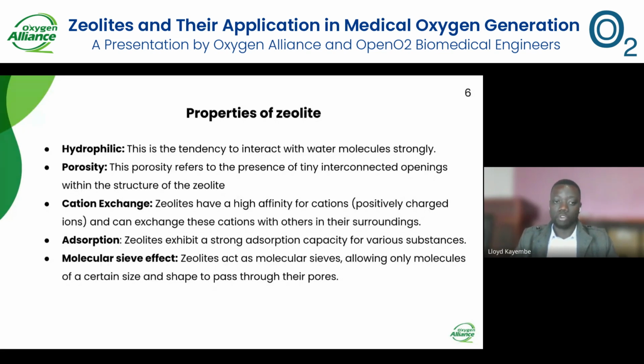The other property is porosity, and this just refers to the presence of the channels and the pores within the structure of the zeolite that allow molecules of smaller size to pass through. As I've said, the sizes of the pores are influenced by the cations that are present in the structure. In the synthetic zeolite that I was talking about earlier, these pores and channels are of uniform size, while in natural zeolite, the sizes of the pores are non-uniform.